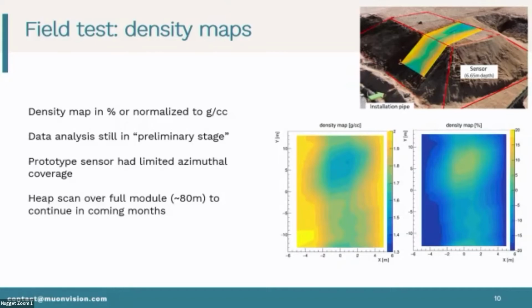We see here density changes. It may seem they're a little bit large. I would agree. Part of the reason is that we don't have a perfect trapezoidal heap, and we have not accounted for differences in elevation, which we can. In fact, this is a representation of the heap scanned by a drone, so we have elevation points at each location in the heap. Incorporating the actual heap shape into our analysis is time consuming, but we don't expect it to be a showstopper.